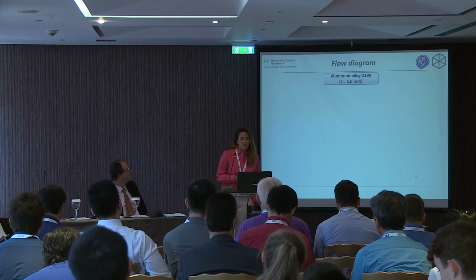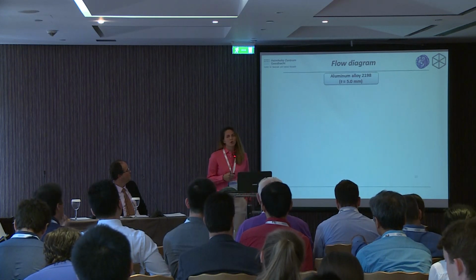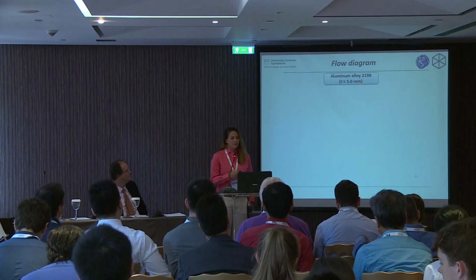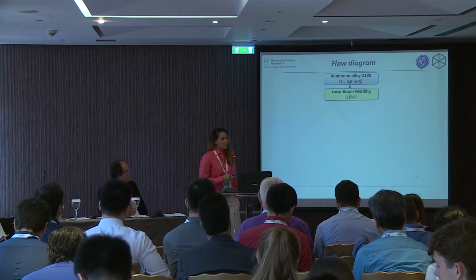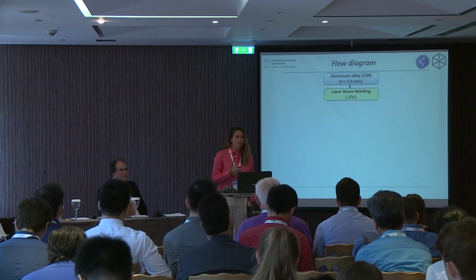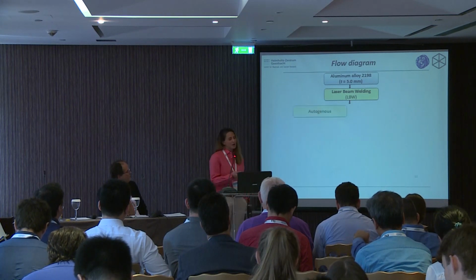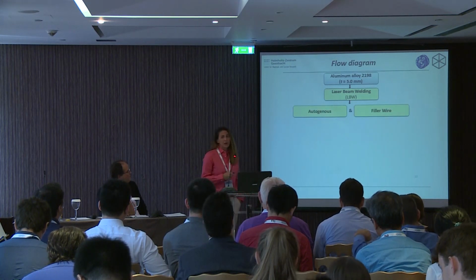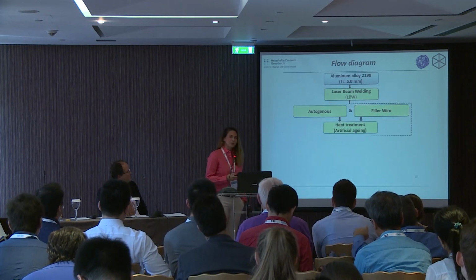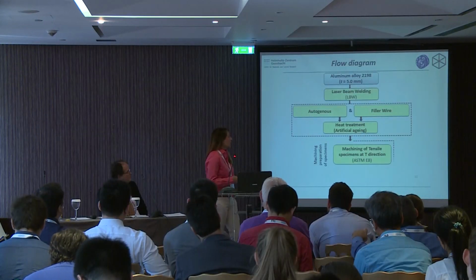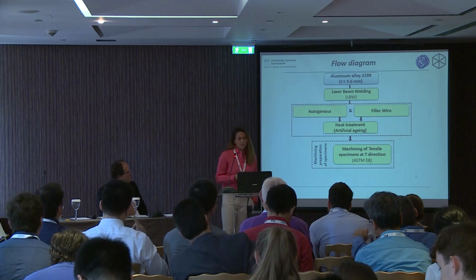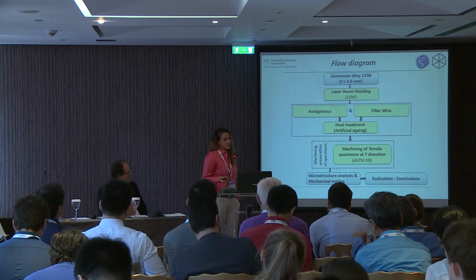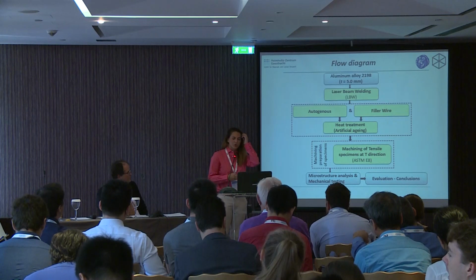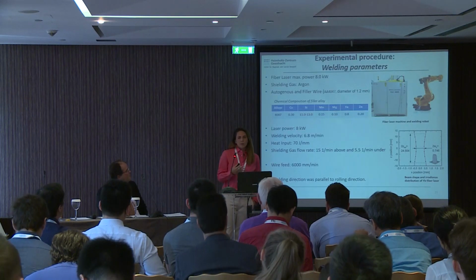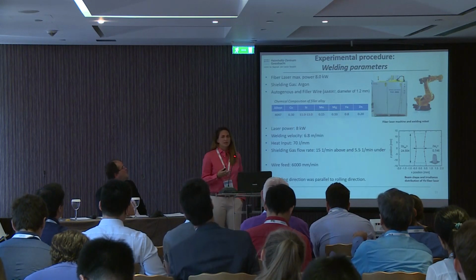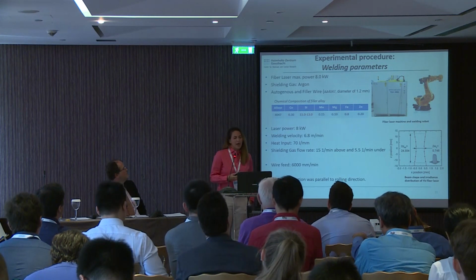For the experimental procedure, we investigate aluminum alloy 2198 with 5 mm thickness. We did laser beam welding for 2 different parameters, autogenous and with filler wire, and some of the specimens were heat treated. We machined the tensile specimens in T direction, and we had the mechanical testing, the evaluation, and the conclusion. For the welding, we used a fiber laser machine with 8 kilowatt power,